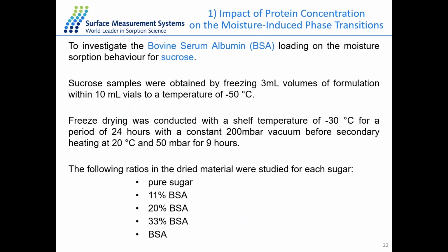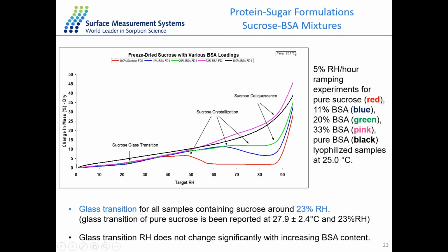So the study we have here, we have the bovine serum albumin protein, and we also have the sucrose sample. And we want to mix the two samples to improve the stability of the sucrose sample. So we have the mixtures in different ratios, and we perform the water sorption experiment, the ramping method as we introduced previously on all of the samples here. So the experiments are performed at 25 degrees, and here's the result. The red line is for the pure sucrose sample, and the black line is for the pure protein sample, and the other lines are just for the mixtures in different ratios.